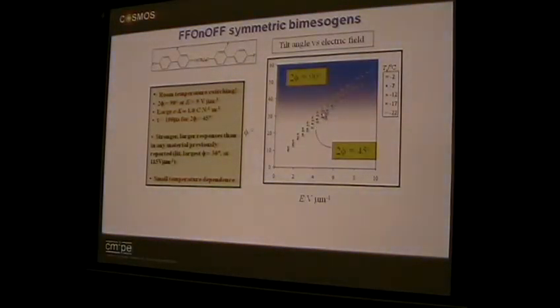The difference in the graphs here is the temperature, and something that is peculiar, if you like, to the flexoelectric effect is that it is essentially temperature independent. Okay, because you have an e over K, a charge over an elastic constant ratio, and they both have almost the same functional variation with temperature, so they self-cancel, they self-correct, to a first approximation.